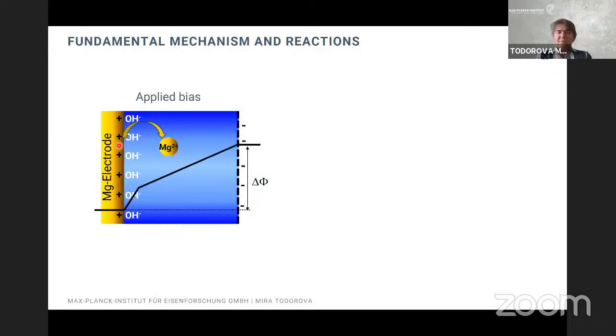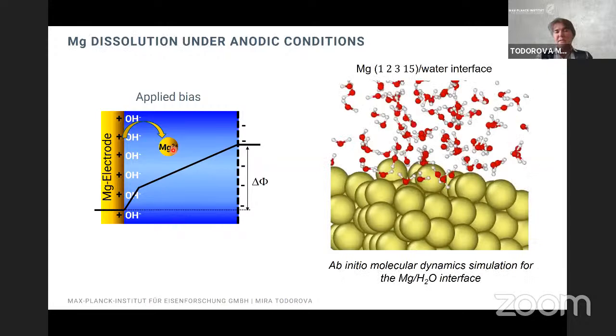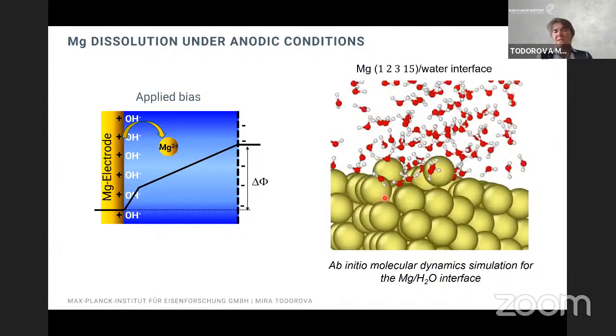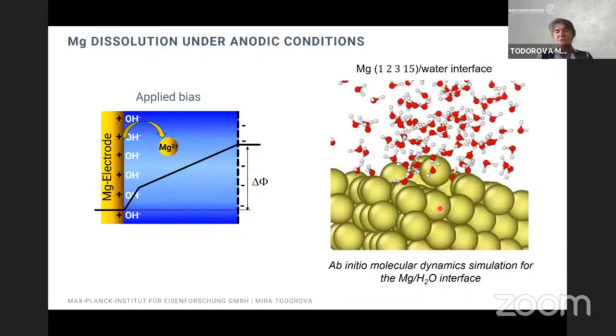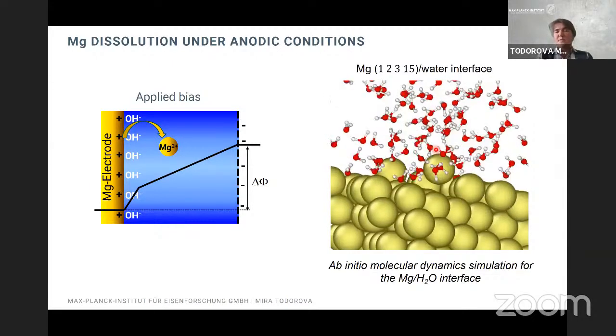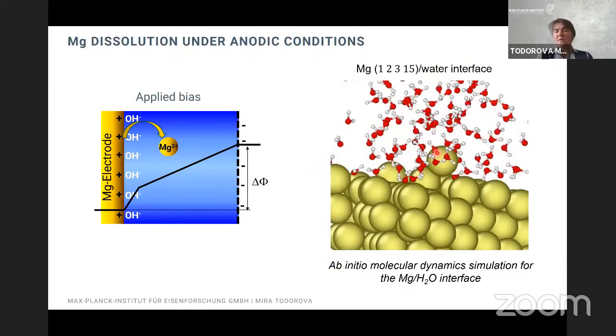Now, if we apply voltage, in principle, what one would expect is that this adsorption at the surface will no longer be sufficient to maintain the electrode potential, and so there will be ions that come into the solution, and we may expect to have some magnesium dissolution. And this is indeed what we can see. So here you can see a molecular dynamics simulation of a magnesium water interface, in which we see that this magnesium atom dissolves from the surface.